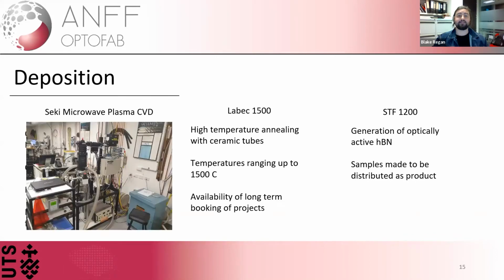Beyond the Seki Microwave Plasma CVD, we have the Labec 1500. Now this is not as technical an area, but it is a tube furnace, which unlike a number of other tube furnaces has the capability of going up to 1500 degrees. This is because it's built out of predominantly ceramic components, which is what distinguishes it from your typical tube furnace, which only goes up to approximately 1200. This one, I would again love the availability of long-term booking projects.